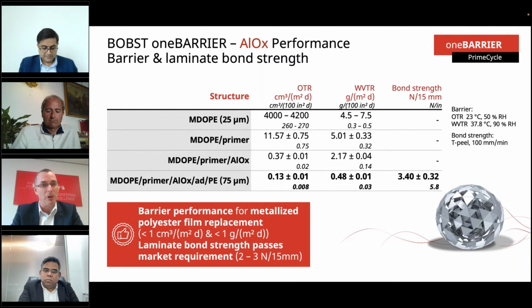With the application of the very thin primer, we can enhance the OTR to a level of around 12 cc's with no real improvement on WVTR. We then add the transparent AlOx barrier layer, which further enhances the OTR to about 0.4 cc's and the water barrier to around 2.2. And finally, with the aid of a barrier adhesive and the lamination to a 75 micron special sealant web, we have an OTR of around 0.2 and a water barrier of 0.5.